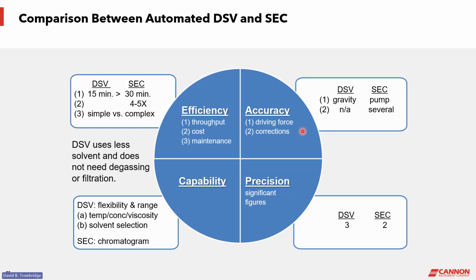And that allows us to maybe jump over to discussing the accuracy. The driving force for DSV is gravity. So that's very stable, as I mentioned earlier. Driving force for SEC is a pump. And a pump has issues with consistency and maintenance. If you do a good SEC work, you should have a marker in your flow to give a measurement of the actual pump rate that's occurring for the analysis. There's corrections that might be needed to get good accuracy. It's really not relevant for the DSV measurements that we were talking about here.